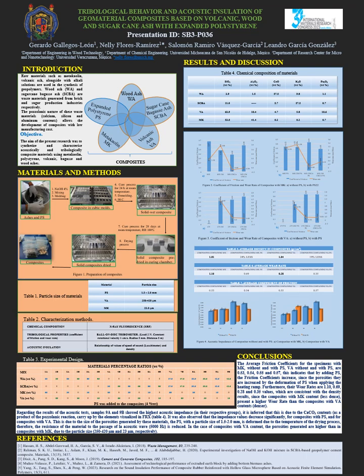Regarding the results of the acoustic test, samples 9A and 9B show the highest acoustic impedance in their respective groups. It is inferred that this is due to the calcium carbonate contents as a product of the pozzolanic reaction carried out by the elements visualized in FRX, Table 4. It was also observed that the impedance values decreased significantly for composite with polystyrene and for composite with volcanic ash.